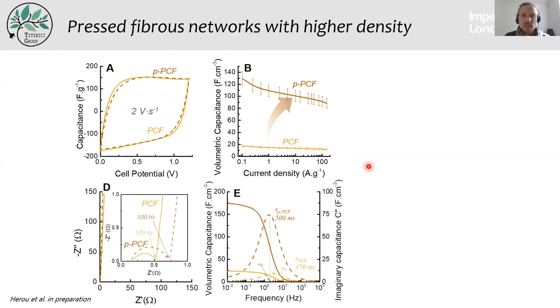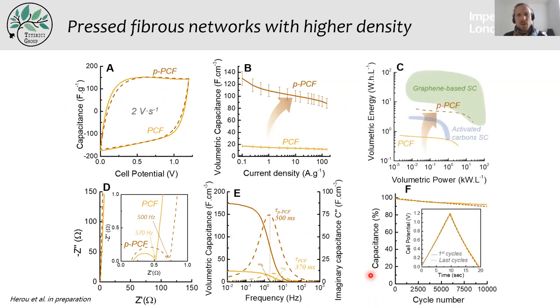And finally, the electrochemical performances, we can see here by comparing the orange to the dark orange line, the non-pressed and pressed sample have roughly similar performances in terms of gravimetric capacitance, but in terms of volumetric, we increase by a large factor the performances. These are the impedance results for people who are interested.